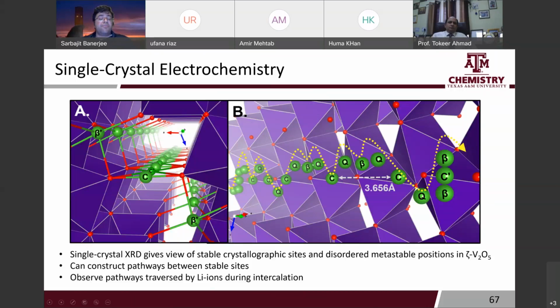So even for a single crystal at one extent of lithiation, as a function of temperature, you can start seeing where the electron density appears, and you can say, okay, that is the path that is thermally accessible to lithium at a particular temperature.